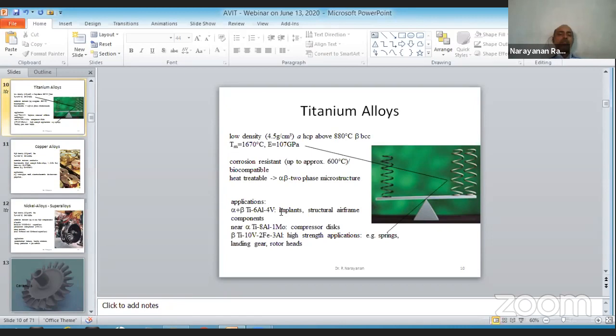Now, what happens is when you place these implants for their other beneficial properties, there's a stress shielding effect. It means this titanium will tend to stay, but the bone will sacrifice. The bone will be the sacrificial lamb. Therefore, research has been going on to make titanium alloys using different elements, for example, niobium, zirconium, with a view of reducing the elastic modulus, say from 130 to 107. People are nowadays even making 60 GPa.